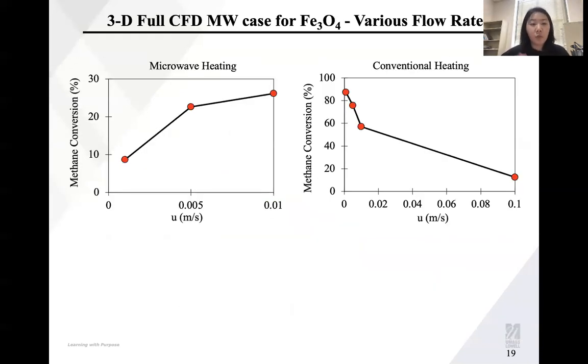And we further tune the flow rate, basically tune the residence time of the microwave reactor as well as the conventional heating. What we found is that as we increase the flow rate for the microwave heating, the methane conversion actually increased. That is so different from what we expect from the kinetics, because as we increase the flow rate, the residence time is decreasing. Then your methane conversion should decrease.